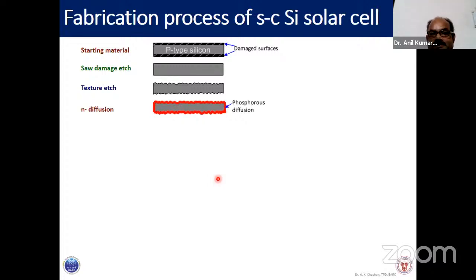And then because it's a P-type surface, now you have to make a junction. In order to make a junction, you dope the entire surface, because you cannot dope it selectively. You can dope selectively also, but usually in the bigger industrial process, the entire thing is put under a phosphorus environment, like POCl3. Once you dope this, you get an N-type surface over this textured surface. So now effectively you have got a PN junction. But if you use it like this, it will be totally shorted from this to this. So you have to cut this part also.